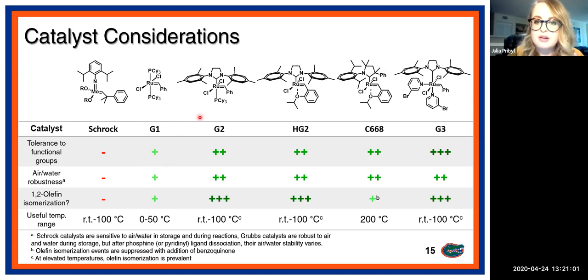Some other later generation ruthenium catalysts are listed here. So these are generally avoided for ADMET polymerizations that are conducted at low temperatures and in solution because, because of the N-heterocyclic carbene ligand on top, they are prone to forming the ruthenium hydride species that can catalyze 1,2 olefin isomerization. And then same thing with the Grubbs third generation catalyst.